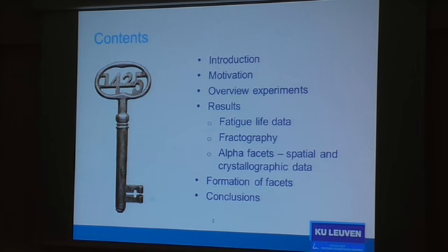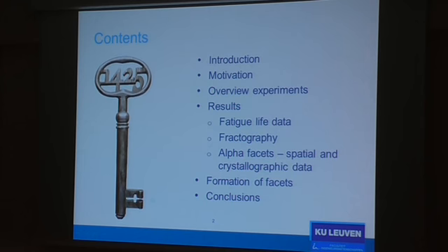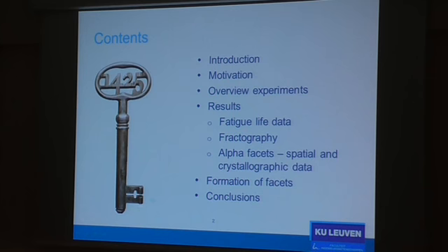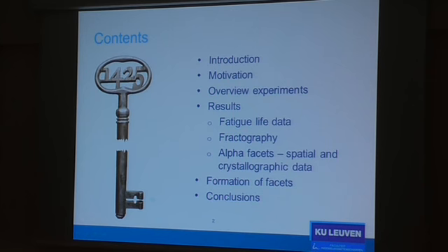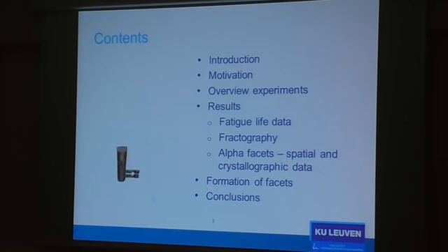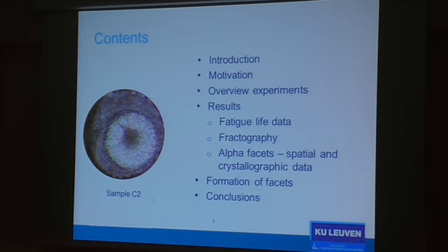Now I am about to explain fatigue to this group, which is a strange thing to do, but I will do it anyway. This is the KU Leuven master key. KU Leuven was founded in 1425. Let's assume that it's made of titanium 6-4, which is impossible in 1425, but we will assume it. We can load it cyclically and wait for a very long time, the stresses are low, until it breaks. In certain cases, we will see that the fracture can start internally and form some sort of fisheye failure. This is an actual sample, where we see an optically dark region, which is the short crack growth region, followed by long fatigue crack growth and the overload fracture here.